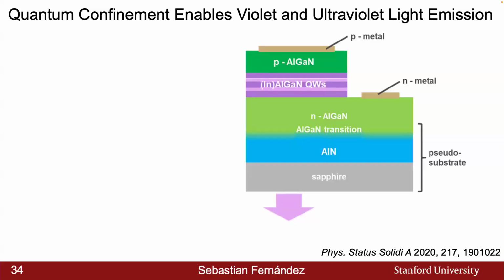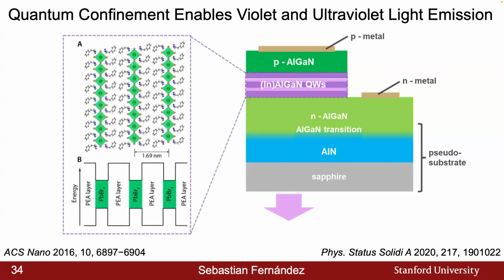So if we look at something like a III-V LED here, we can focus on this indium aluminum gallium nitride quantum well structure, in which by using quantum wells, we're able to artificially increase the optical band gap of the material by confining the states within the material itself. And it turns out we can play the same trick here. So we've already looked at this material, but in general, we can quantum confine this lead bromide octahedra between these organic phenethylammonium layers, creating the same quantum well structure.